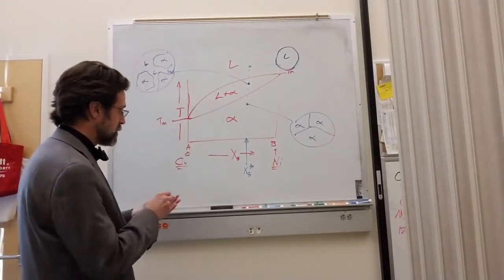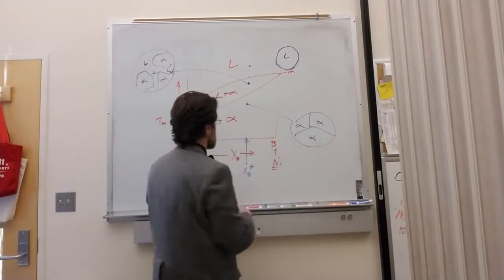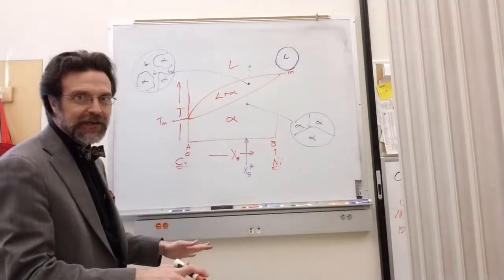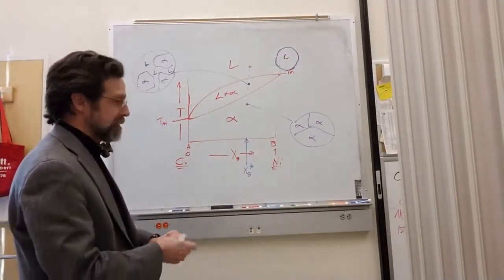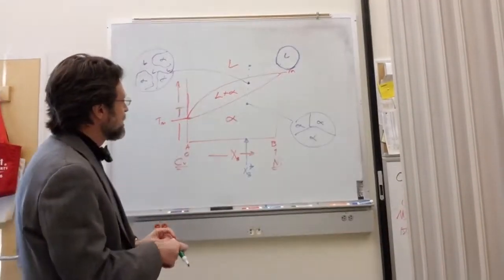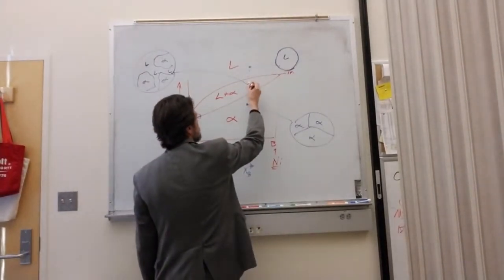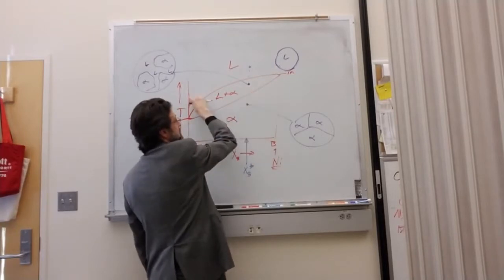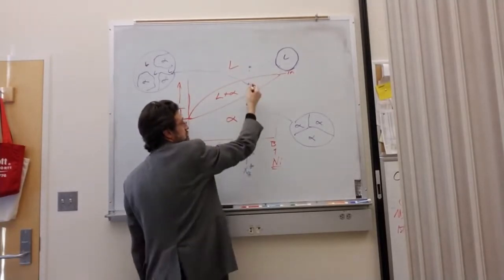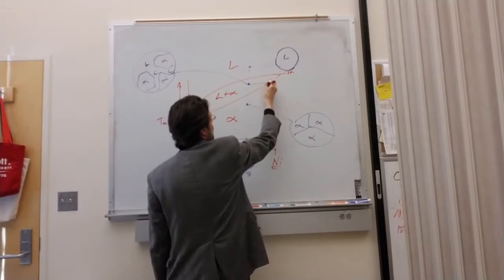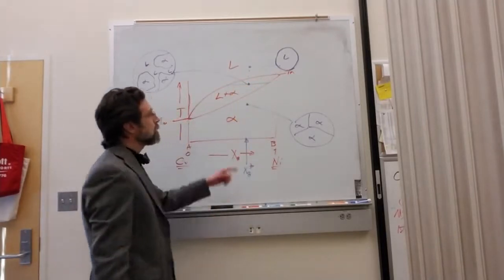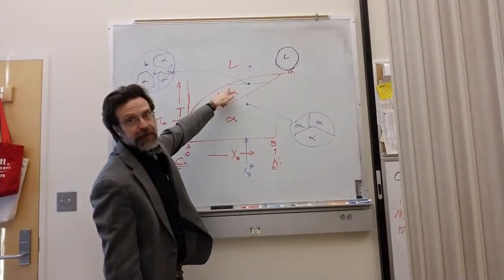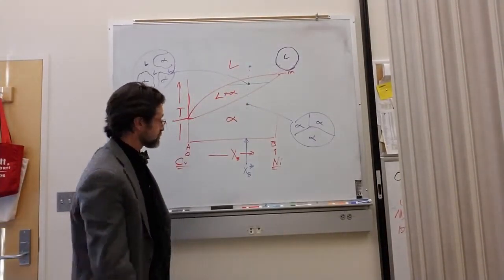And to do that, we draw a horizontal line. We call it a tie line, and I don't know why we call it a tie line, but that's what all the textbooks call it. I call it a horizontal line. So you draw this horizontal line through the point you're at in the phase diagram. So you've got the temperature and the composition. And you look at where that horizontal line touches the phase boundaries in our diagram.